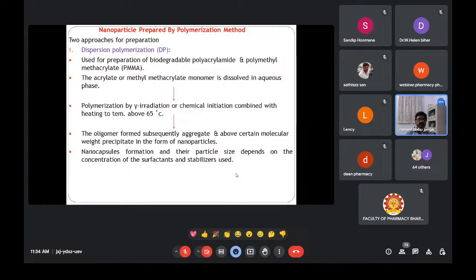The polymers formed subsequently form aggregates, and above a certain molecular weight they precipitate in the form of nanoparticles. So don't feel that aggregates are dangerous at all times. While preparing, they form aggregates and combine to form a nanoparticle. This is what I would like to emphasize, that the term aggregates leads to the nanoparticles by applying your standard conditions of preparation. Nanocapsule formation and particle size depend on the concentration of surfactants and stabilizers used. So this is a valid point. What type of surfactant or polymer is being used and what stabilizing agent we are using in the formulation, based on that we are going to frame the nanocapsules.